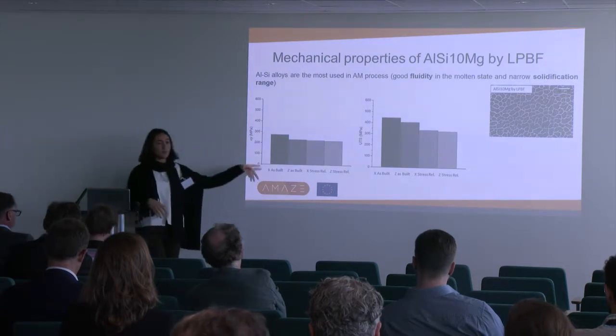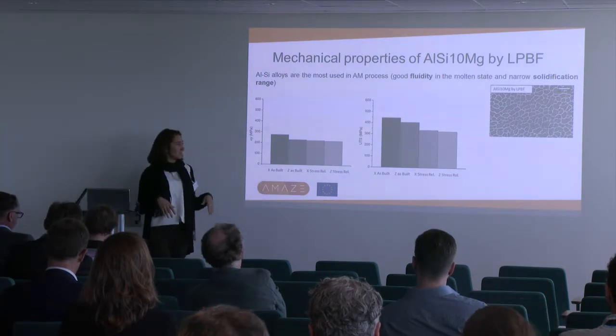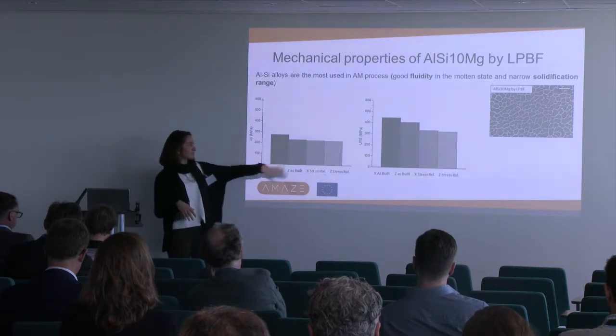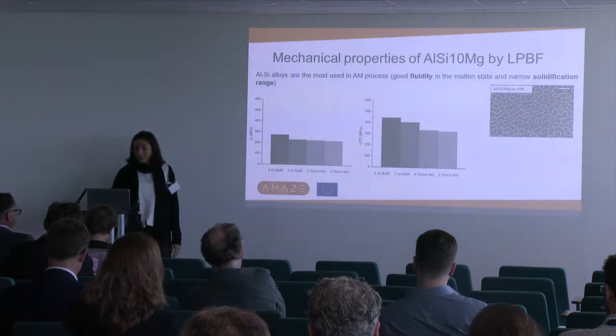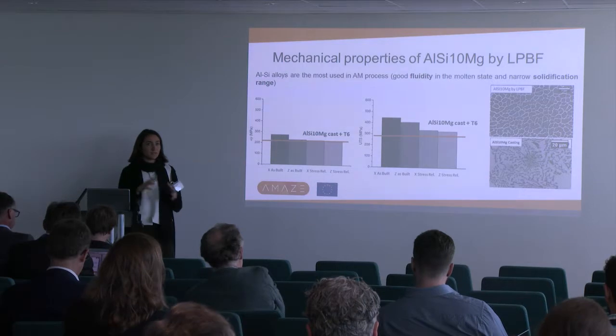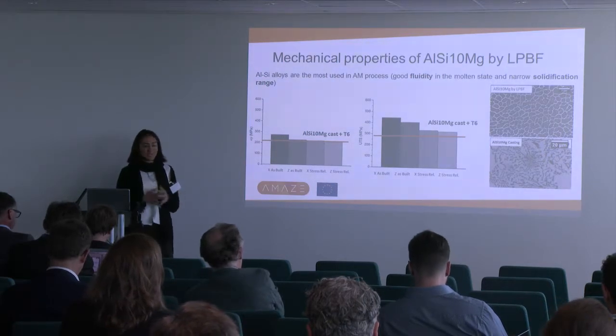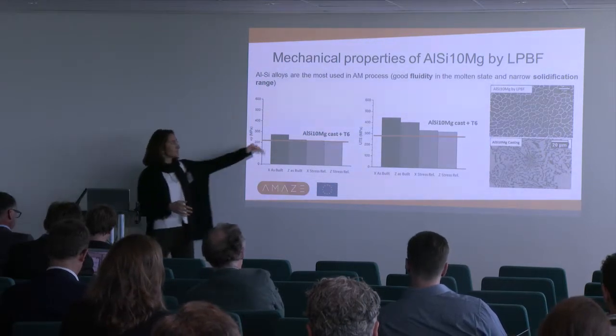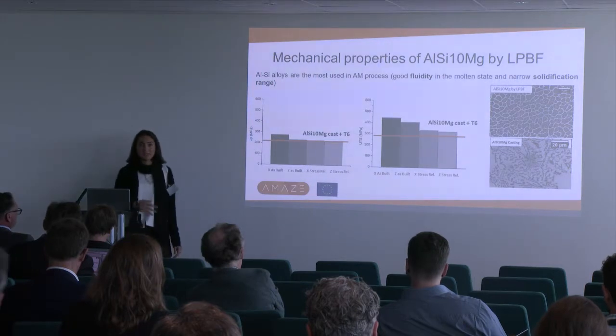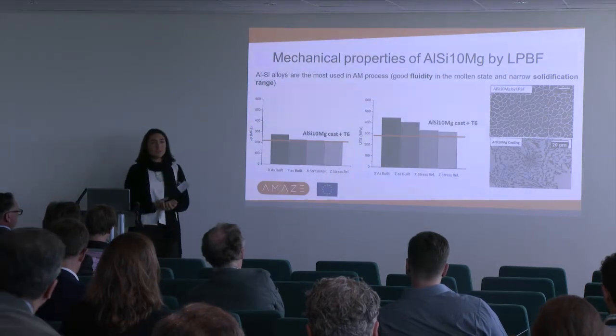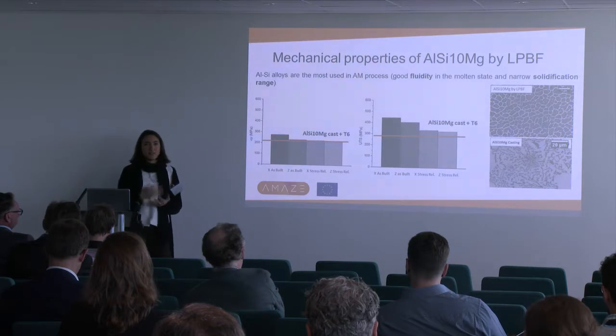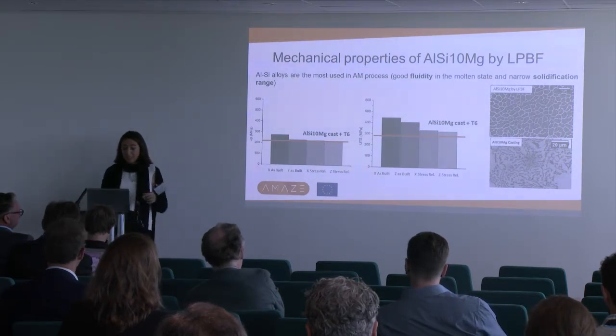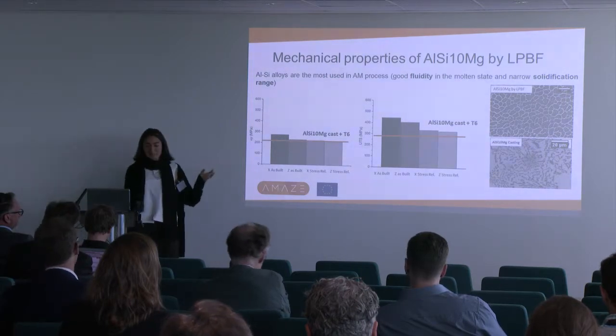Here we have the mechanical properties of the aluminum silicon 10 magnesium alloy in different conditions. So we have the yield strength and the UTS. And if we compare these mechanical properties with the mechanical properties of the same alloy made by casting and T6, we can see that we always have higher mechanical properties in all conditions. So this is the real advantage from a material science perspective of the additive manufacturing process. So this is really a promising thing.